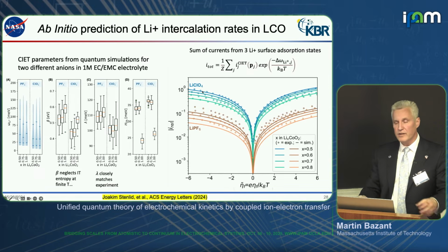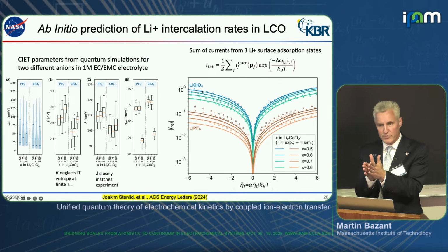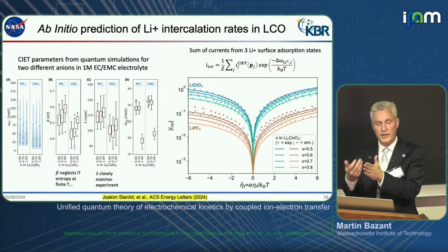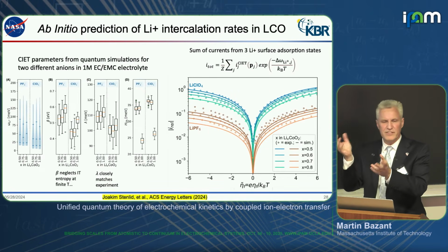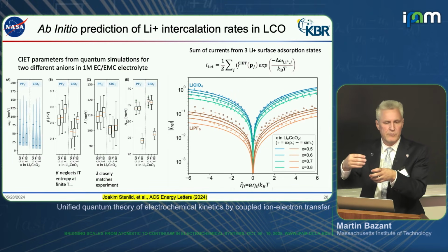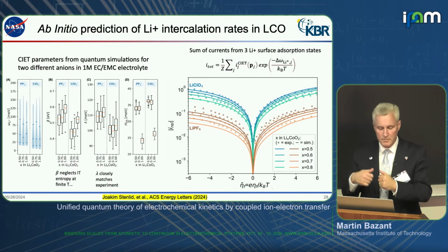The one parameter is the active area or number of active sites, because in the end we make a very thin porous electrode. We try to operate it under reaction limited conditions, and we can estimate from BET analysis or things like that what the active area is, but it's pretty hard to exactly count the number of active sites. We fit basically an overall prefactor, okay?